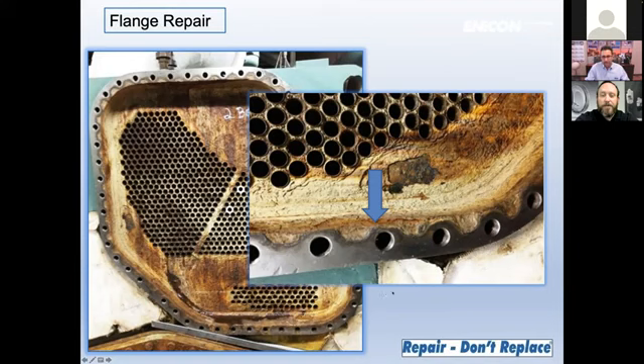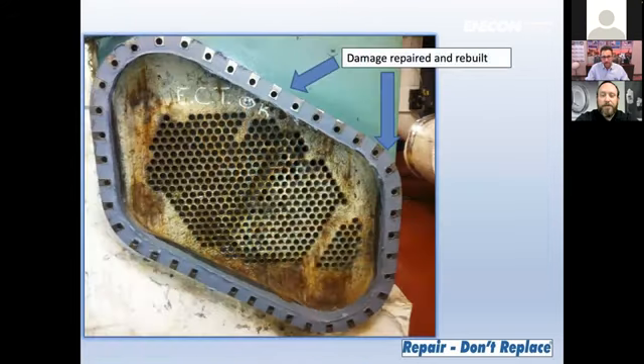This type of repair is typically completed in one day and put back in service the following day. The first thing we do to complete this application is complete surface prep on the areas, creating a clean, dry, rough surface to both the tube sheet and end covers that are going to be rebuilt. After the surface prep is complete, ENECON's Duralloy material is applied to the surfaces, typically overbuilding the damaged flange areas in order to rebuild the flanges back to specification.